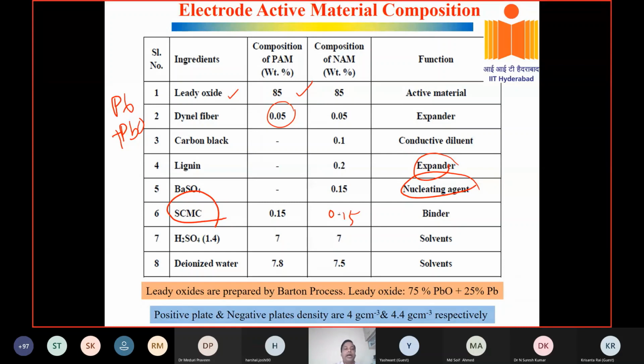as a binder. We use 1.4 specific gravity sulfuric acid, 7%. We use deionized water around 7.5% as well. So we take all the things and do the mixture. In the mixture, we put everything and mix them thoroughly, and then we prepare a paste.